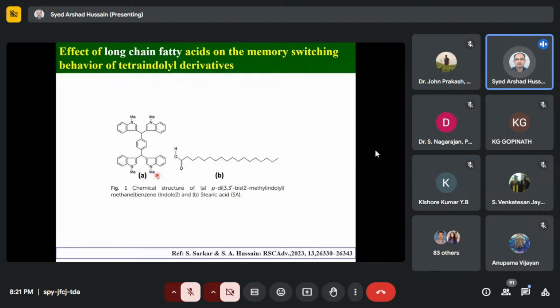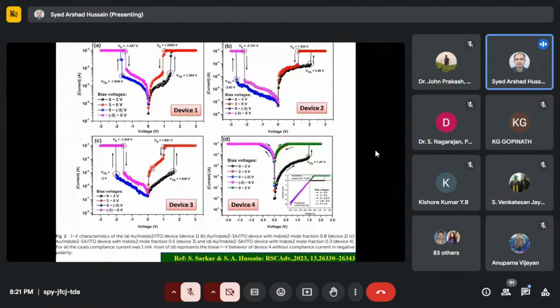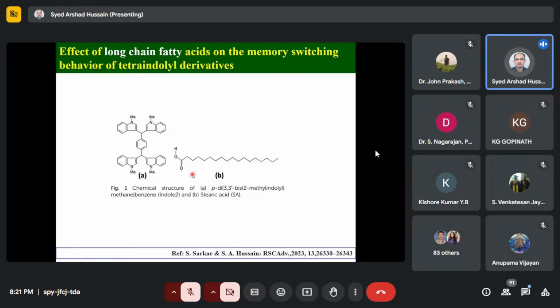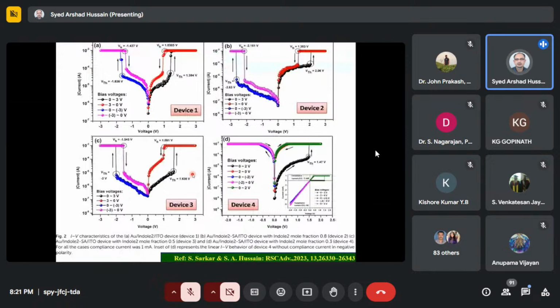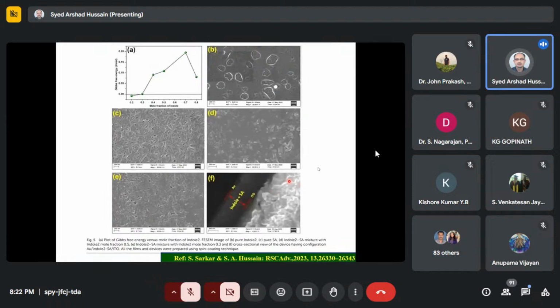Okay, then again we studied another indole derivative, and we found that initially it does not show non-volatile switching. It was volatile threshold switching. But when we mixed this molecule with stearic acid in suitable conditions, we found that it shows WORM, write once read many, kind of behavior. So these are some morphology of the device. Then this is a cross-sectional image, and we have seen that in the presence of stearic acid, some pores form, and we expect that due to this long alkyl chain, this may act as a charge trap. So once it forms the channel between the two electrodes, it can trap the charge, and the channel remains for a longer time.